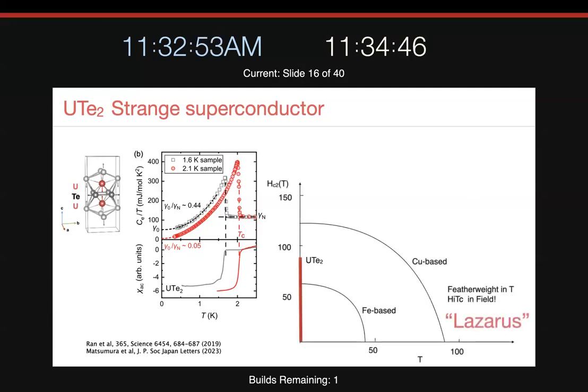So what's remarkable about this system? Well, it's been called a Lazarus superconductor because it has an upper critical field that swims with the big guys. It's a heavyweight system in a field, but it's a featherweight system in temperature. So this is the phase diagram compared with the cuprates and the iron-based systems. Its Tc is basically 0 compared to these systems, but its upper critical field is known, in one particular set of directions, to exceed 80 Tesla. How can a 2 Kelvin superconductor have an 80 Tesla upper critical field? This is a fascinating question in an era where we're trying to produce high field magnets. If we could understand this, maybe we could make new kinds of high field magnets.